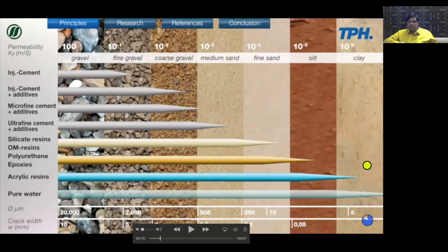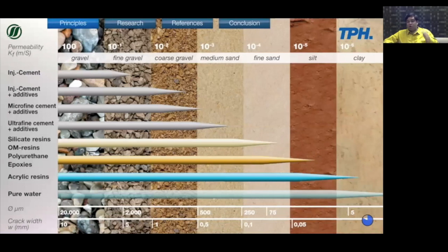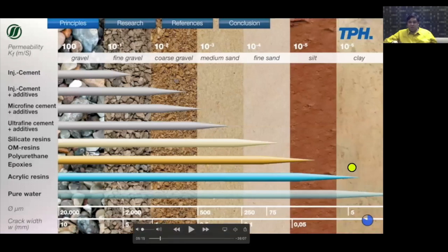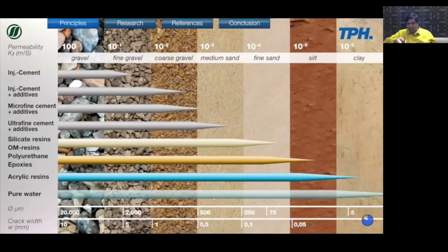And then your acrylic resins are extremely, extremely low in viscosity. I think, if I'm not mistaken, our basic rubber tight, vario tight systems have viscosities as low as, I think, 2 to 3 mPa·s, which means almost like water. Water is one, so this one is just hardly 2 to 3, and it's very close. So it can reach almost all the places that water can reach. Hence, it can even be used in strategies where you're trying to consolidate or hold clay together. And of course, the last one just shows you water, the least viscous of it all, and it can pretty much go through all the different kinds of sand strata. So permeability is basically the basis on which we actually select. It is one of the guidelines in selecting the right material for the right application.